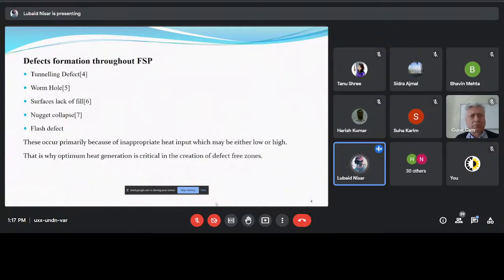Now the wormhole. This is a cavity caused by the lack of convergence of material flowing across different zones due to lack of material driving force. It is most noticeable at the junction of the stir zone and the thermomechanically affected zone on the advancing side. This defect is primarily caused by less rotation speed. Another defect is surface lack of fill. It is also a type of void, which is majorly caused when the pin length is too short in comparison with the plate thickness. It is also caused by low heat generation.